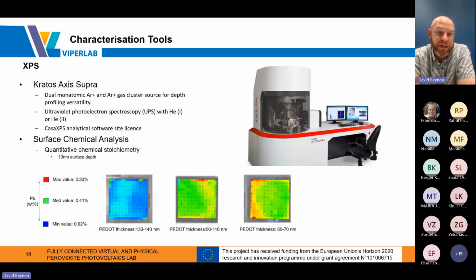Another example of characterization equipment we have available, which we can apply to our coating, is the XPS system. So we have a Kratos Axis Supra XPS system available. It does UPS, but what we tend to use it for in relation to coating is for surface chemical analysis. So it can do quantitative chemical stoichiometry up to 10 nanometers of surface depth. If you want to check the conversion of a chemical, perhaps tin oxide.